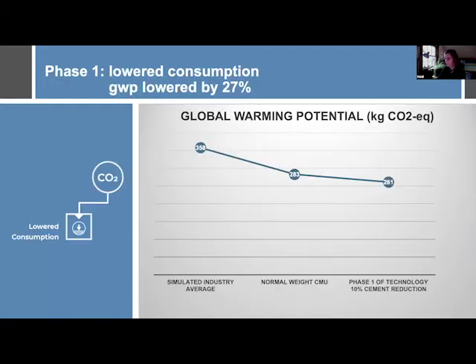So here I have phase one of what we've done with this technology, which is lower our cement by 10%. And so I have a simulated industry average here. The reason I'm calling it simulated is because it uses our plant data with an industry average mix design, because our industry did not do an industry average. So I kind of made my own, and I did it just for myself. I was interested in it, but it's not a true industry average, but it kind of gives us a starting point. And here is what our global warming potential is from our normal weight CMU. And then reducing our cement, it brings this down to 261.